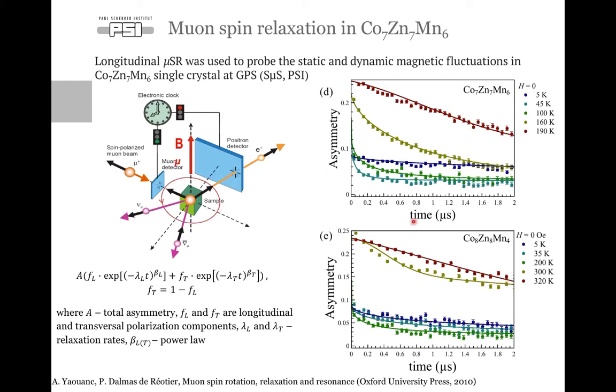Here I show you the asymmetry functions measured from 0 to 2 microseconds for samples cobalt zinc manganese 776 and 884, measured at different temperatures at zero magnetic field. Immediately we can see that above the ordering temperature, we have only very slow decay of the asymmetry function, just because we don't have any static magnetic ordering in the sample, and the paramagnetic fluctuations are too fast to be measured with muons. They're just outside of the muSR sensitivity window.